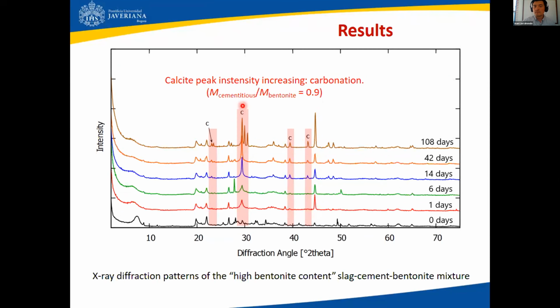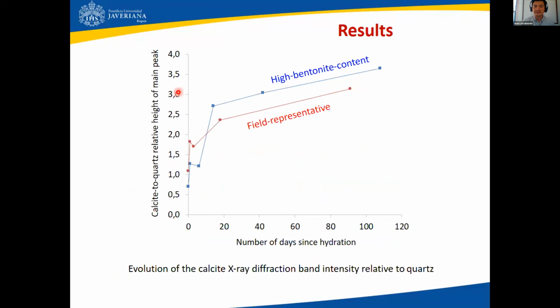So what we confirm here is carbonation. We believe carbonation is taking place because in this case, CO2 from the atmosphere is being absorbed, let's say, by the mixture, and the calcium specifically reacts with it in order to produce calcite. And in fact, no other calcium carbonate polymorphs were found in this particular study, only calcite.